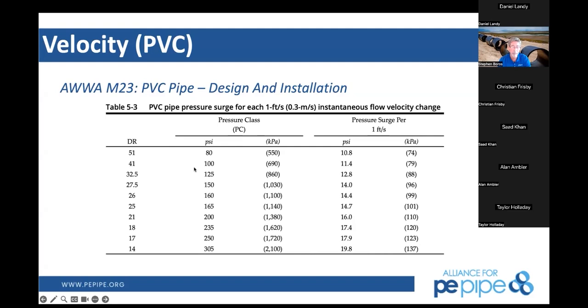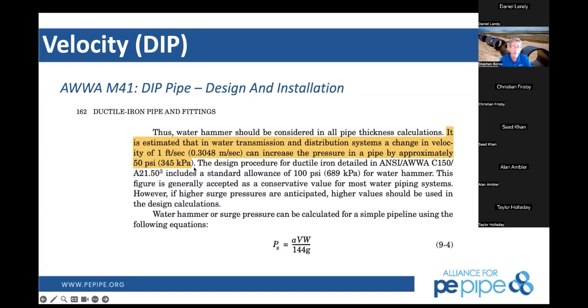So ductile iron will be similar, polyethylene will be different. You mentioned here for ductile iron, this is out of their design and installation guide, M41. For every foot per second change, you will have an increase in pressure by approximately 50 psi. That's pretty high. And so again, it's a strong material. It can handle it as long as it's designed properly and the working pressure is not too high. So you have the working pressure plus this surge, which has certain limitations you have to make sure you stay below.